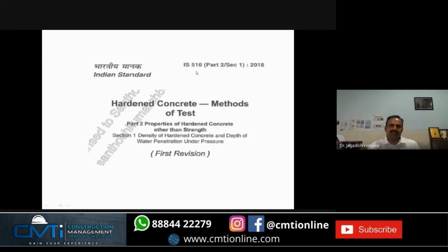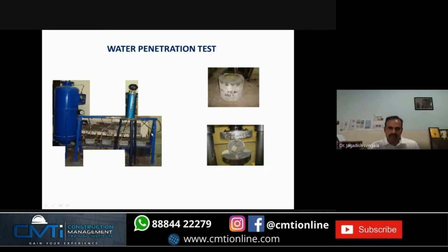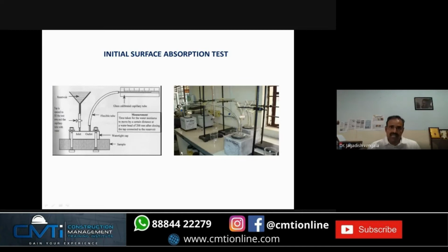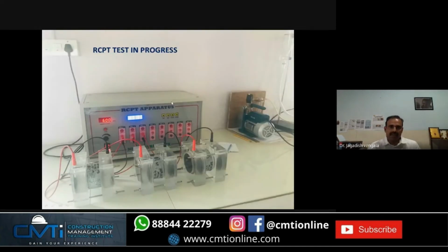Very interesting, IS 516, 2018, they've added new tests other than the strength tests. What are those? Water penetration tests, and then initial surface absorption test, very important test, and RCPT tests. These are the three very, very important tests when you are making SCC. SCC usually you make it for tall structures and other applications, particularly high strength applications also.